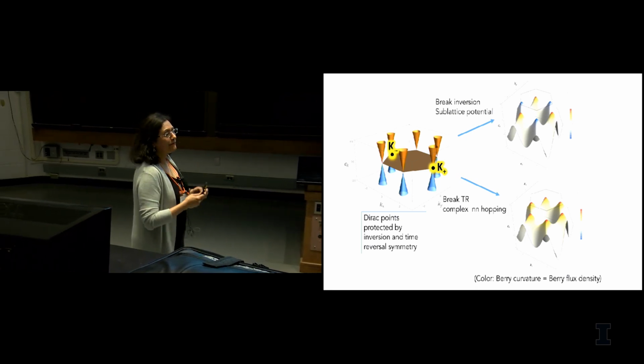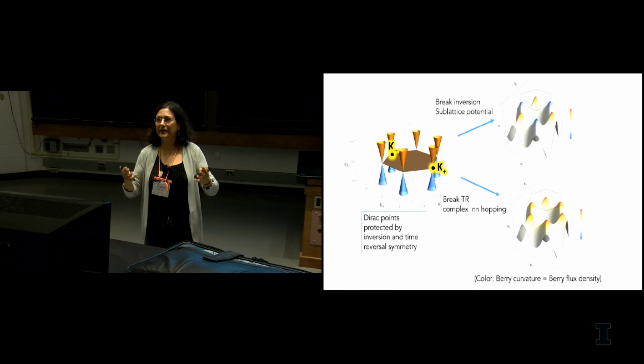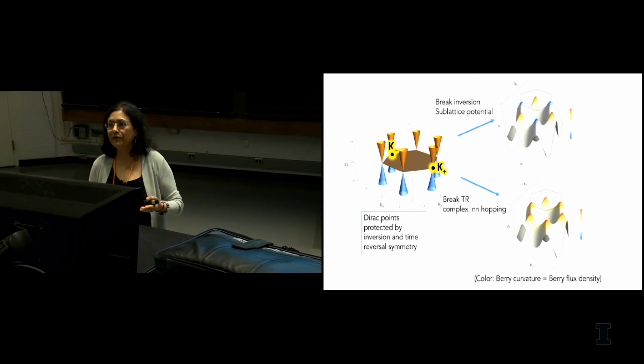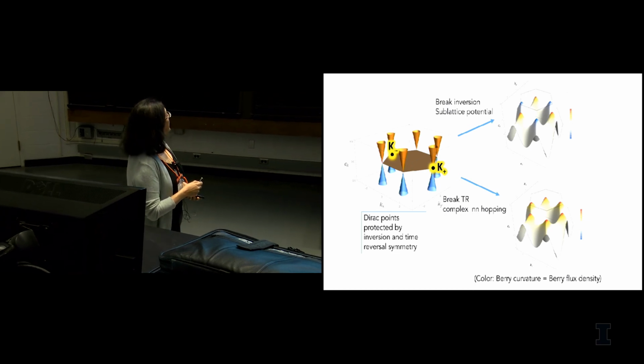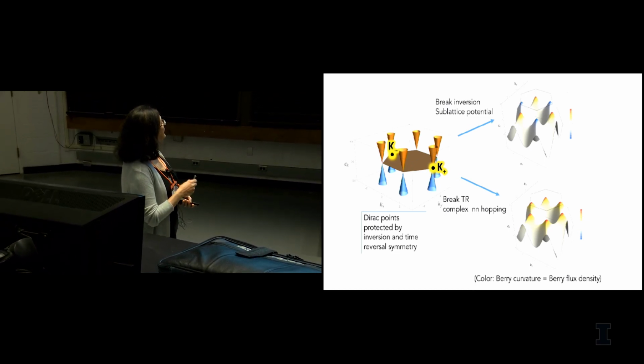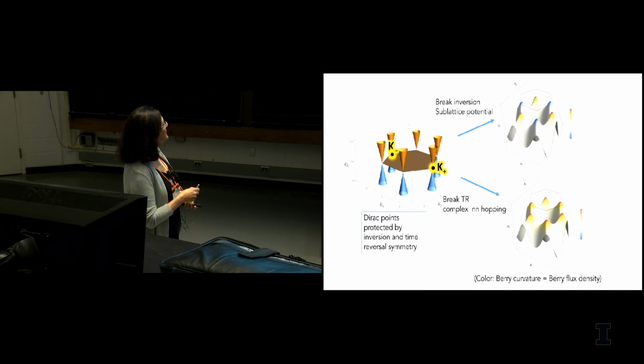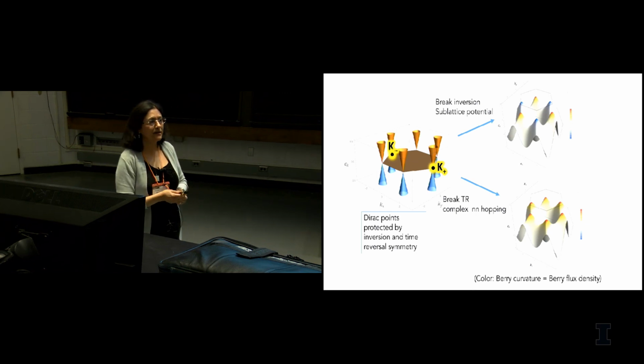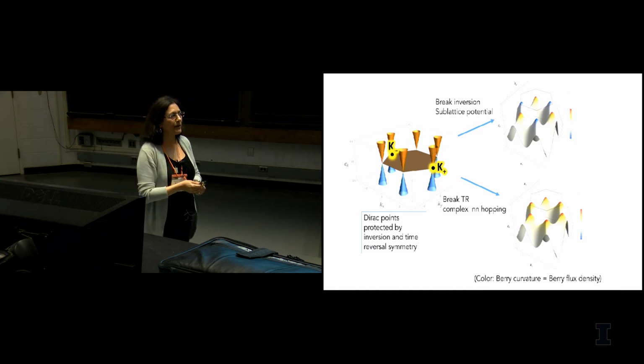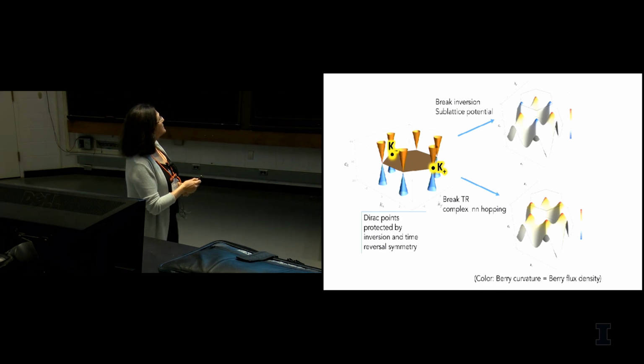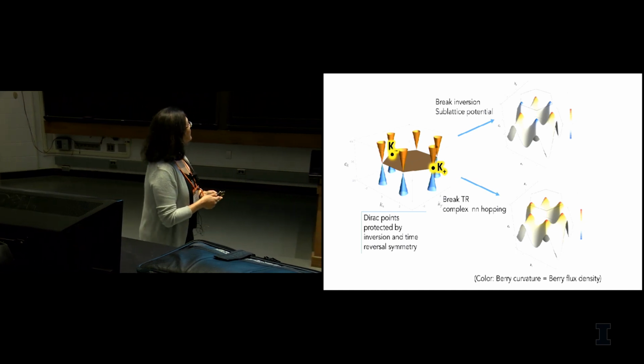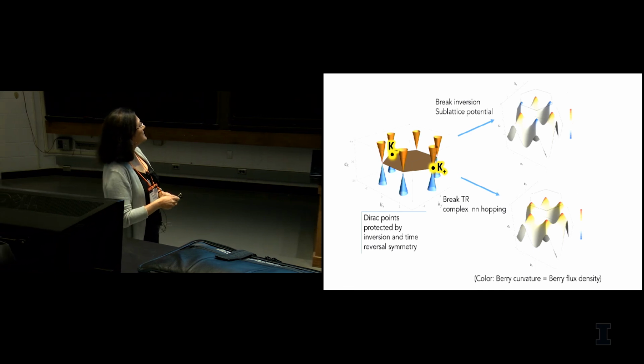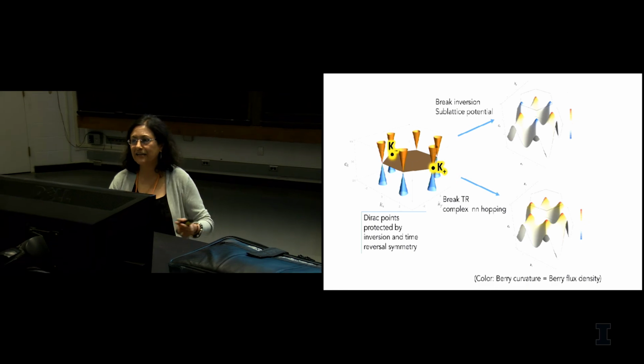So we are looking at graphene. There's really no getting away from graphene today. It's become a paradigm for several phenomena. If you look at graphene, you can see that it has these K and K prime points, these Dirac points that are protected by inversion and time reversal symmetry, and you can break them in two ways. This is just by putting some sublattice potential, which gives you these red and blue, essentially the Berry curvatures at these K and K prime points, and they have opposite Berry curvatures. But you can also break it by breaking time reversal invariance, and then you get a Berry curvature which is the same on all the points. So that's like a Chern insulator.